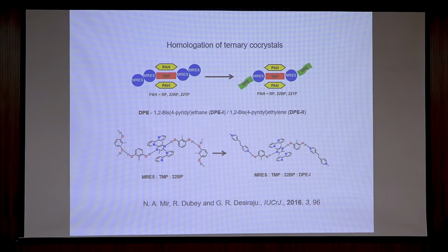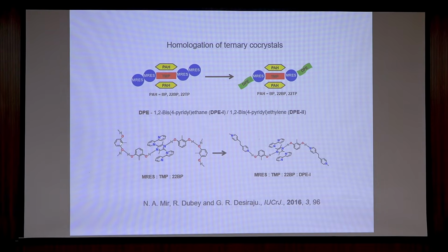Now these two fellows, I talked about Ritesh, this is Niaz, and we had this ternary co-crystal: tetramethylpyrazine, and this is some polynuclear aromatic hydrocarbon which stacks. Then there is a hydrogen bonding to this 2-methyl resorcinol, and we all noticed that the 2 hydroxy groups in 2-methyl resorcinol are non-equivalent. One is hydrogen bonded to nitrogen, the other one to oxygen. So they are non-equivalent. Chemically they are different.